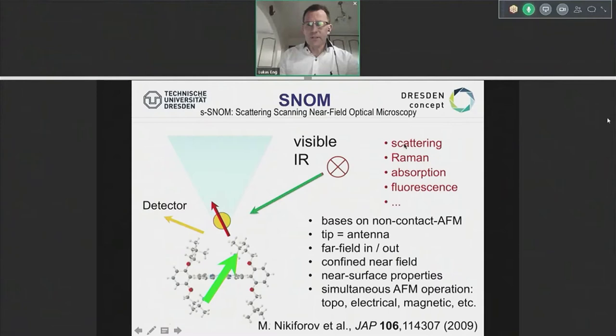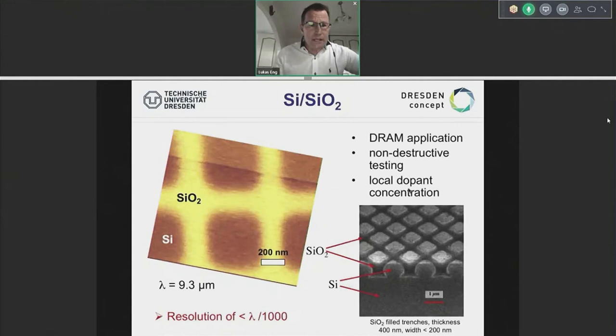You can do scattering. That means elastic scattering, looking at the same energies. You can also measure the Raman spectrum, which is vibration. You can also measure the absorption by scanning the wavelength here. You can also look at the fluorescence with this kind of technique. So too few things have been done so far, simply also because too many techniques have been lacking, for instance, also the light sources. So we've done some examples, and it would simply break the ice for some kind of material contrast, which is really the chemical contrast between silicon dioxide and silicon on a very industrial DRAM sample,